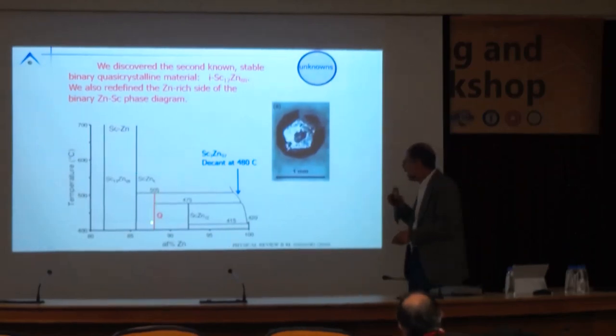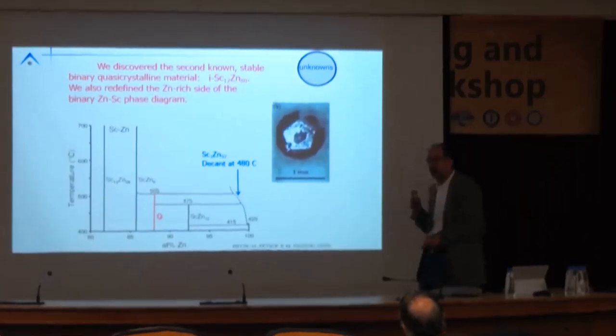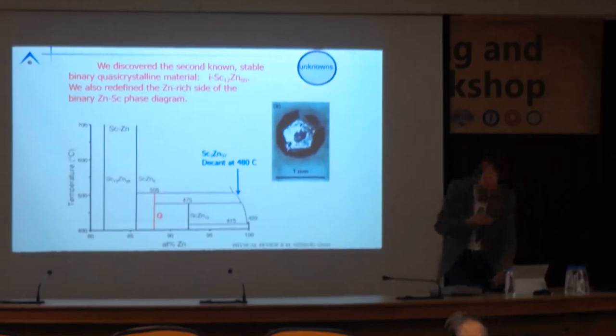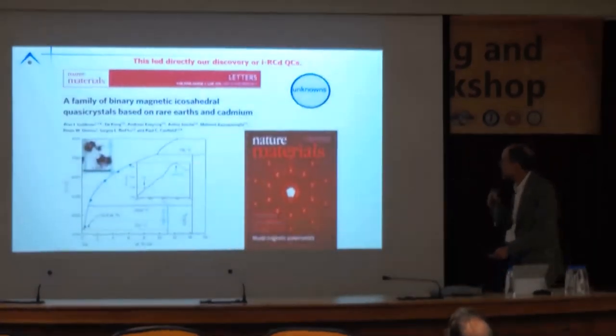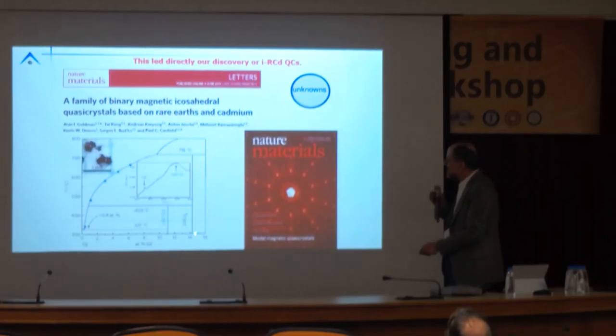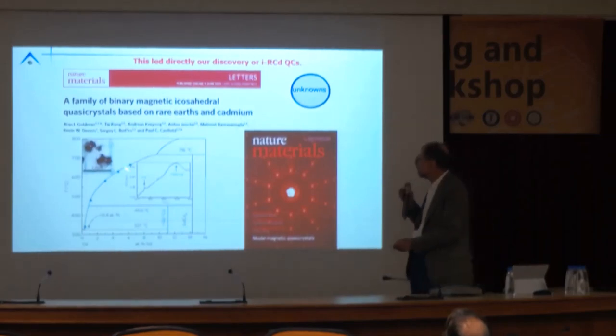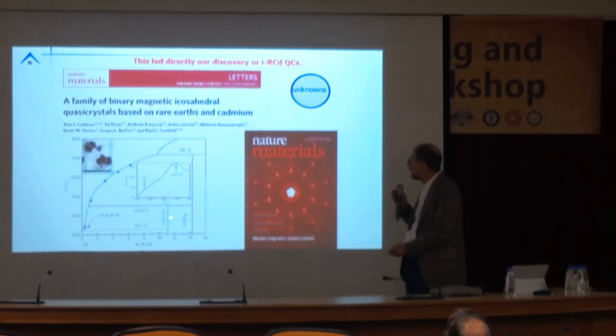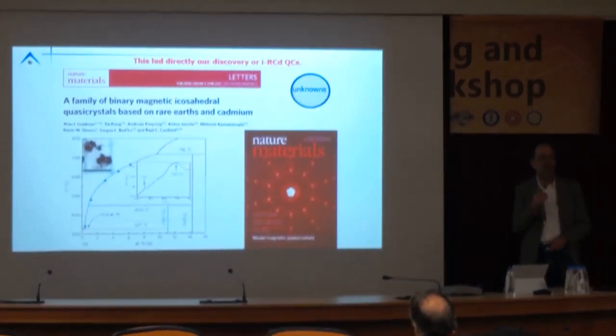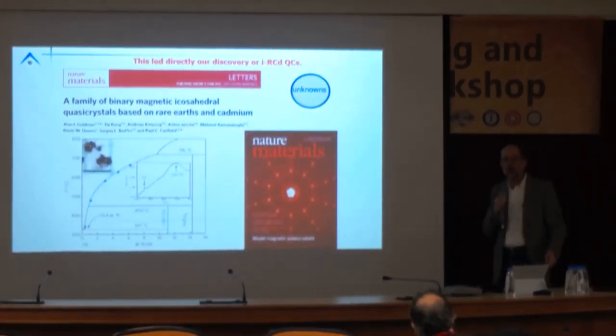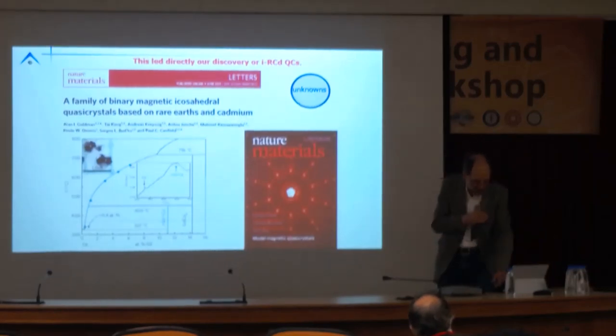What we speculated is, my God, there might be a lot of deeply peritectic decomposing quasicrystals next to approximants. I wonder if we could find others, okay? And we left it there until my colleague and dear friend Alan Goldman said, hey, what about gadolinium cadmium 6? That's a crystalline approximant. So we went into this system explicitly wanting to see if we could find an undiscovered quasicrystalline phase. And indeed, we did. We found a gadolinium cadmium icosahedral phase shown here. And more importantly, we could go up for yttrium as well as other rare earths out to erbium or thulium. So it was a new family of binary quasicrystals that had local moment magnetism, and we can look at spin glass or not spin glass physics.